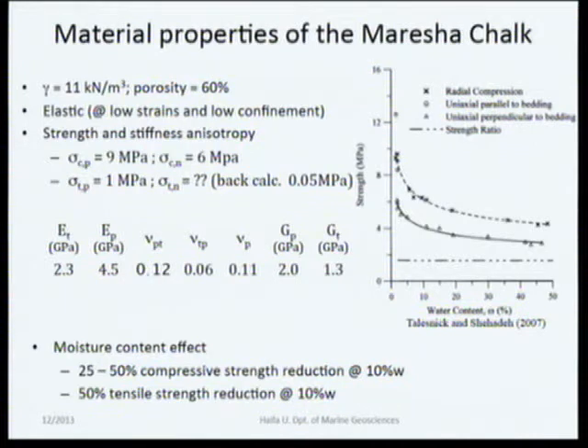And more important than the values per se, it is the effect of the environmental conditions that makes this material very, very interesting. In the plot on the right side, you can see the strength of the material as a function of water content, W. This work was done by Talesnick and Shehadeh in the Technion. You can see very nicely that at higher water content, the rock loses strength very rapidly. In some cases, the rock loses about 50% of its strength given 10% water content. This has to be accounted for in the analysis. We cannot incorporate it as is into our model, but we can account for it in our interpretation.